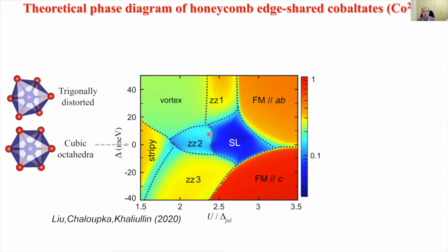So here is a generic phase diagram for cobaltates in this type of bonding geometry, where the vertical axis characterizes how isotropic the environment is. So cubic octahedra would correspond to the 0 point here. And then the vertical axis is a trigonal distortion. And one direction is compression, and the other one is elongation along the direction normal to this plane. The horizontal axis is related to electron correlations, where here is the Hubbard interaction, and delta is some charge transfer energy between the oxygen and cobalt.